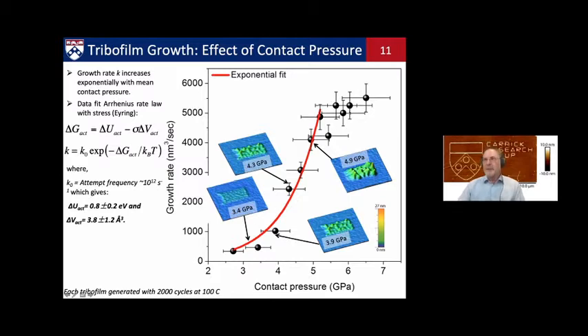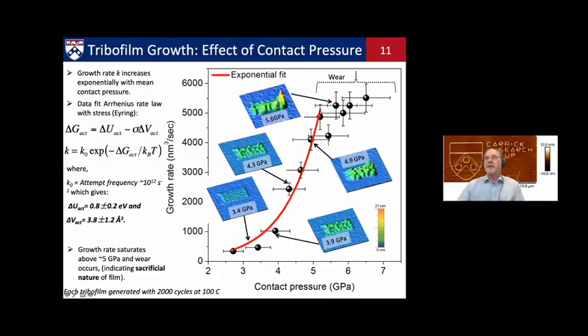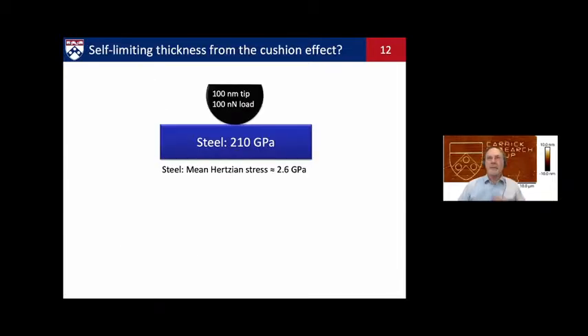If you grow the film at too high a stress, you do get a film, but you also see this competition between growth and removal. So here is this zone where there was some film that then was removed, and you can see some pileup from moving that around. You can see no longer a clear exponential benefit to the stress because now this other process of wear, removal by the sliding, is taking place. So that helps shed some light on what might be going on.